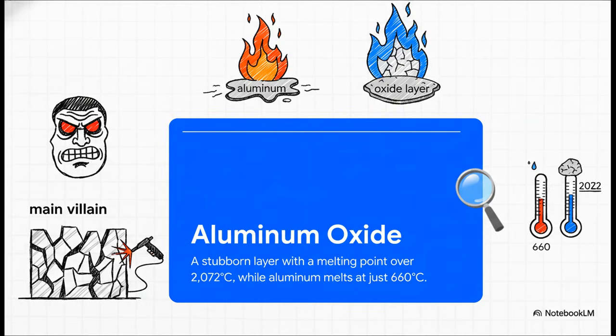Meet the villain of our story, aluminum oxide. This stuff forms instantly the second aluminum hits the air. But check out those melting points. The aluminum underneath turns to liquid at around 1200 degrees Fahrenheit, but this oxide layer on top won't even break a sweat until it's over 3700 degrees. It's like trying to melt a chocolate bar that's trapped inside a ceramic mug. If you don't get rid of that mug, you're just not going to get a good weld.